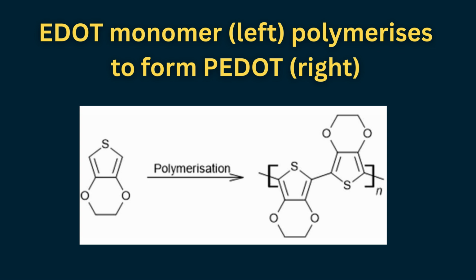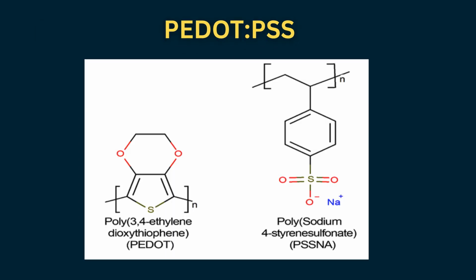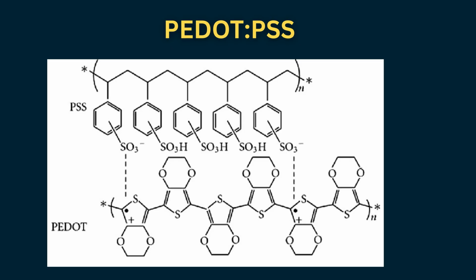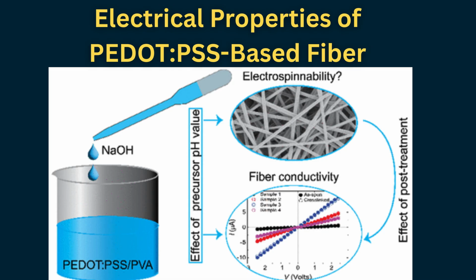Pristine PEDOT is insoluble. Therefore, it is commonly combined with polystyrene sulfonate, PSS, to form PEDOT:PSS. PSS acts as both dopant and stabilizer, coating PEDOT to generate nanoscale particles dispersed in water as stable colloids. PEDOT:PSS is a p-type semiconductor valued for electrical conductivity, solution processability, and visible transparency, making it highly suitable for optical and electronic devices.